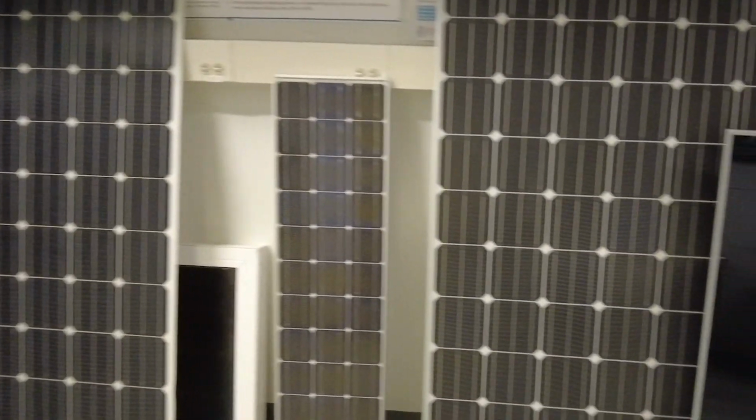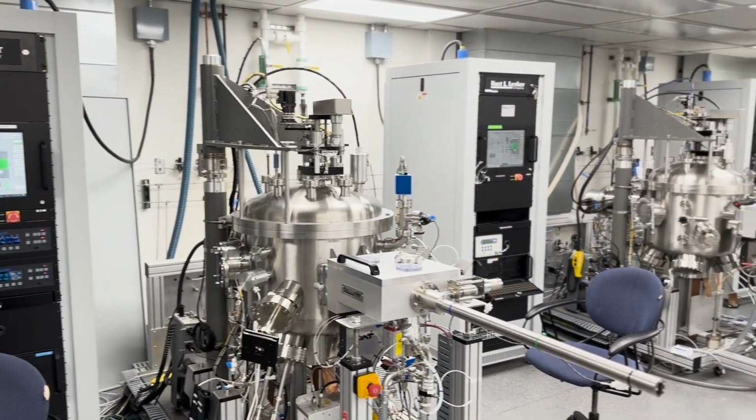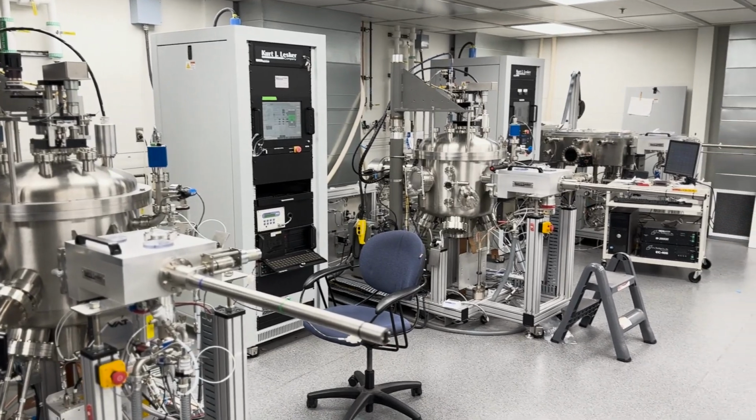So they have a high absorption coefficient. That means you can make an ultra-thin absorber layer to harvest all the sunlight energy. And this material can be processed using a solution-based method or a low temperature vapor-based method. So you can significantly reduce the manufacturing costs and the energy input to fabricate the material. It's also special for its defect tolerance property. So instead of making single crystal material, we can make polycrystalline thin film. And that shows pretty good efficiency and minimizes energy loss.